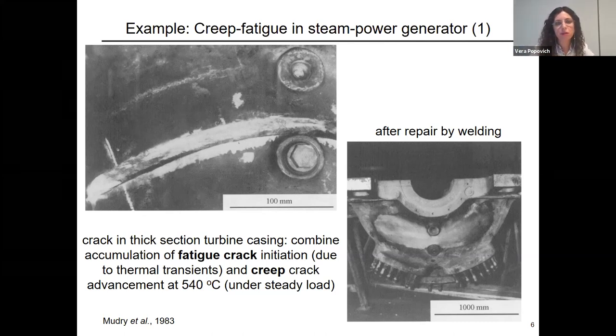And what happens in this particular case is that a crack initiated in the thick section of the turbine casing, due to this start-stop accumulation. It's the most dangerous when you have these transients between 150 and 200 degrees, in this particular case between the steam admission valves. And the fatigue crack in this particular case is initiated due to these thermal transients. But what is important to keep in mind is that the initiation of the fatigue crack is not enough just for the complete failure. In this case it was found that it's actually a combination of fatigue and creep.